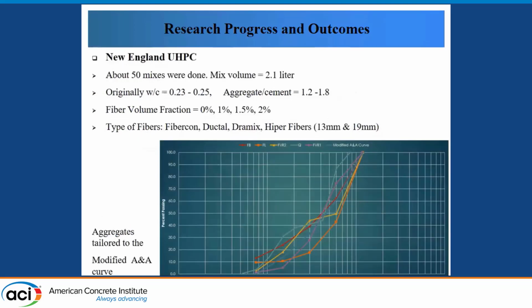Once we finalized the optimized mix, we moved towards the actual UHPC matrix. We mixed around 50 UHPC concrete mixes at a volume of 2.1 liter each time with water cement ratio 0.23 to 0.25 and aggregate to cement ratio of 1.2, 1.5, and 1.8. Aggregate particle distribution was tailored to follow the modified Andreasen and Andersen curve.